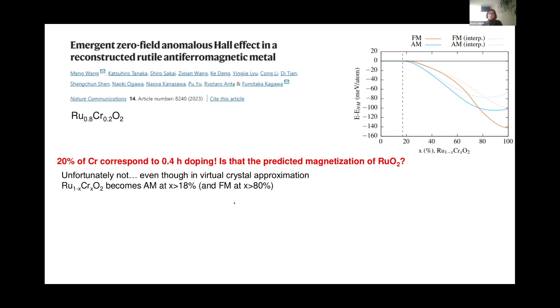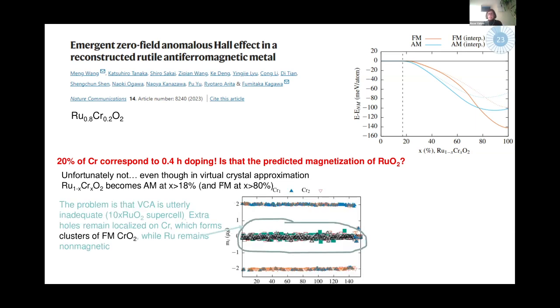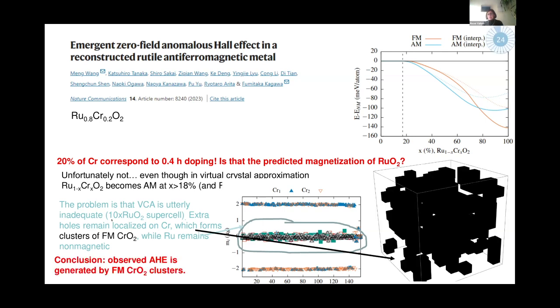So what Andriy did is, well, this is a very rough approximation, we should do supercell calculations, and this is what he did. If you do supercell calculations, so then you really take very large supercells and you insert this 20% chromium, the reality is very different. What happens then is that chromium likes to cluster and ruthenium doesn't acquire any magnetic moment. So what is formed in the crystal, and this is what is shown in this nice simulation, is that the chromiums cluster and they form ferromagnetic clusters. And what these measurements are probably measuring here is the clustering of chromium dioxide. And because it's ferromagnetic, they will get, in fact, an anomalous Hall signal.